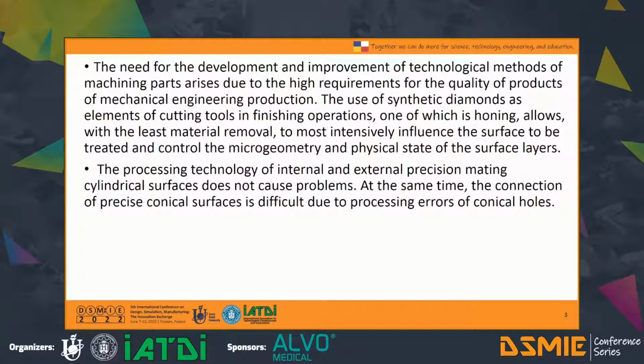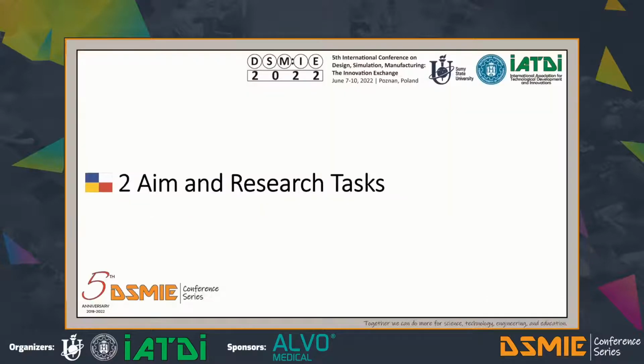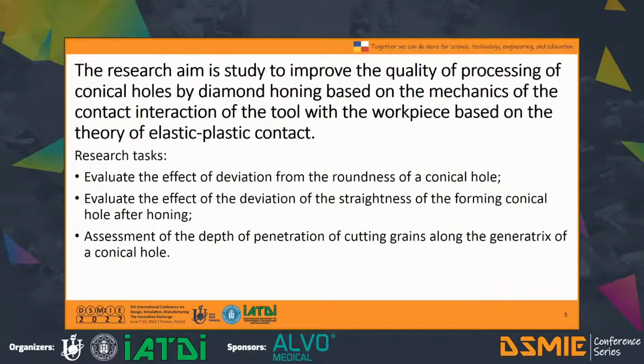The processing technology of internal and external precision mating cylindrical surfaces does not cause problems. At the same time, the connection of precise conical surfaces is difficult due to processing errors of conical holes. The research aim is to improve the quality of processing of conical holes by diamond honing, based on the mechanics of the contact interaction of the tool with the workpiece and the theory of elastic-plastic contact.